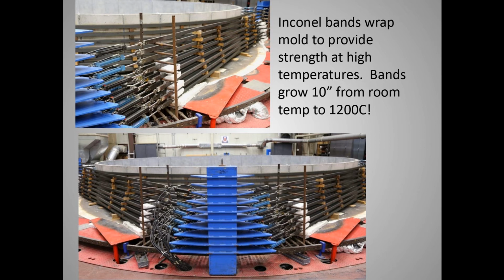Inconel bands, heat-resistant steel wrap around the tub walls to keep things together. They expand 10 inches from room temperature to 1,200 degrees C. So they're terminated in these air cylinders, and they're fed by dry nitrogen on board the spinning part of the oven, so that the same force is applied as they move 10 inches from room temperature to full heat.